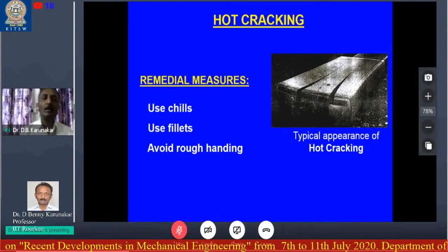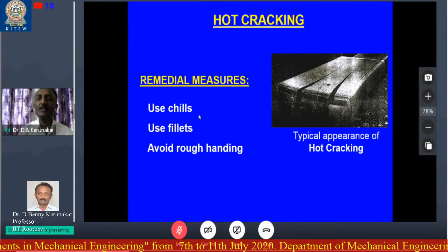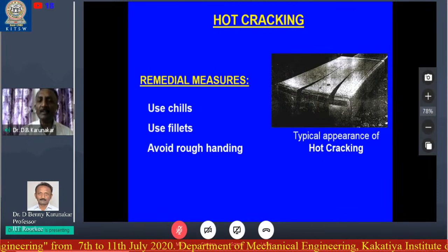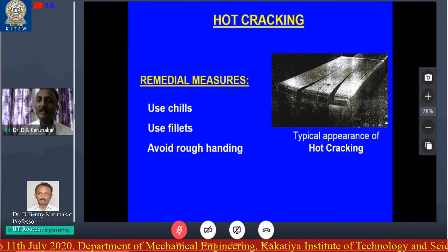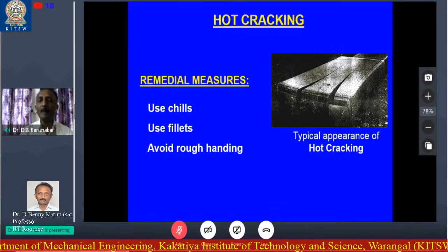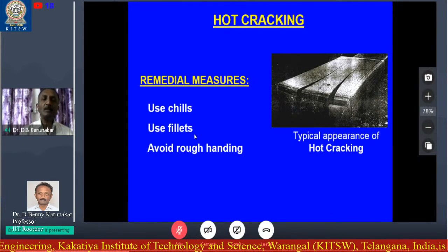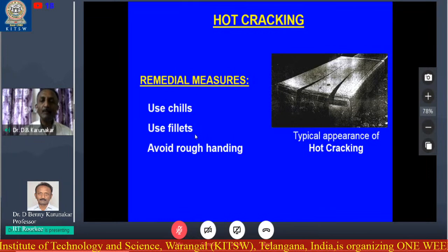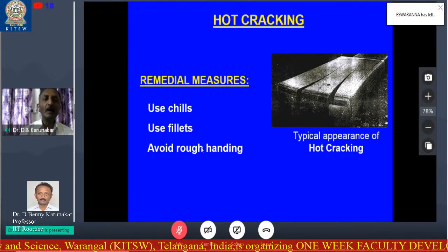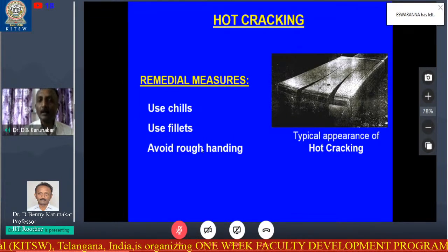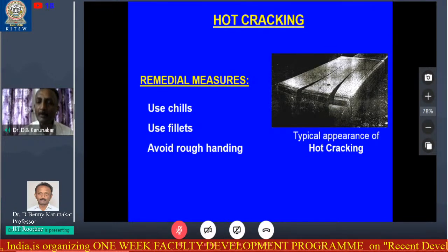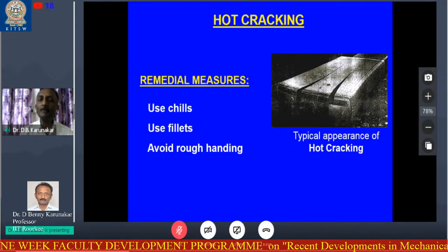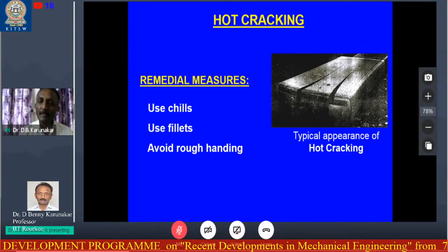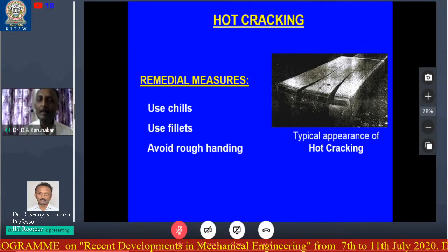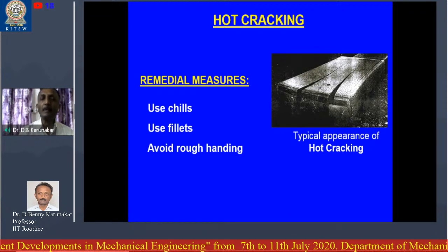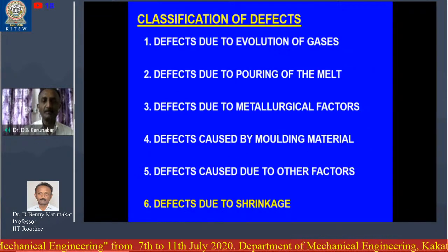Remedial measures: use chills. Chills are the steel blocks which are kept inside the molding boxes, so that there will be uniform cooling of the casting. Next one, use fillets. These fillets also will help uniform cooling. Avoid rough handling. After the pouring is over, after solidification is over, and especially be careful during the knockout process, be careful during the heat treatment process, then this defect can be minimized to a greater extent.